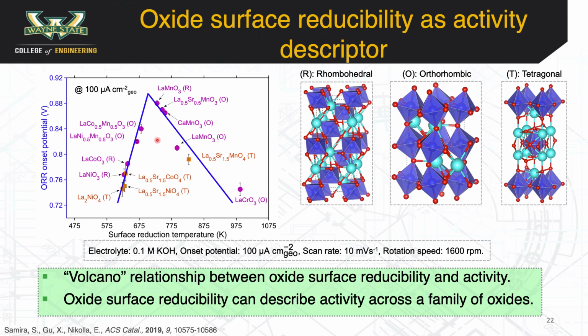Lastly, this descriptor captures effects from the crystal structures, stemming all the way from rhombohedral to orthorhombic to tetragonal structure, making oxide surface reducibility global in describing the electrocatalytic activity across a family of oxides.